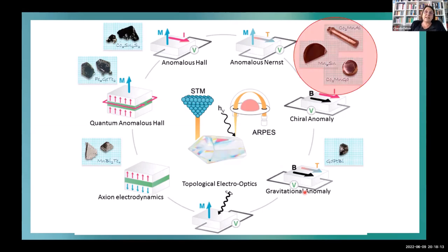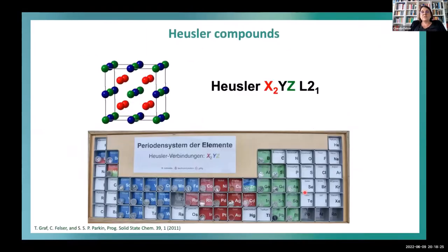So I want to stay at the beginning with the Heuslers, and I'm not sure whether I can go much farther because of time. There should also be a little time for questions, but maybe I can show more or less all the principles. As before, everybody knows I like Heuslers. They are very simple, they are cubic, and they can be made out of many elements. So this is a nice thing, we can tune them. If you want certain properties, especially ones which we can then observe in transport, we really need to tune the material a bit. As I mentioned before, there's an inflation of Weyl semimetals and ferromagnets, and only a tiny fraction, I would say a per mille of compounds, has been discovered so far. We can mix more or less the whole periodic table together and grow a crystal.